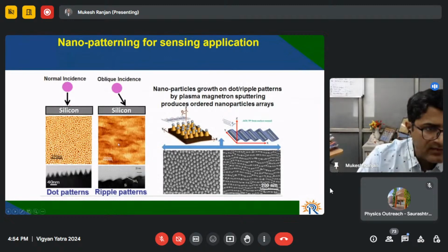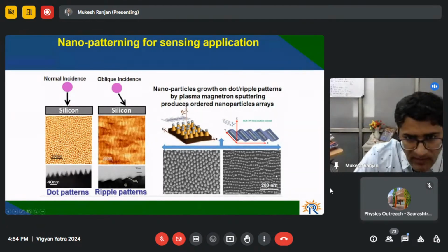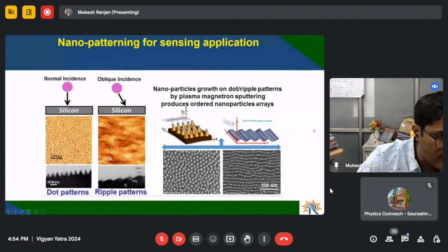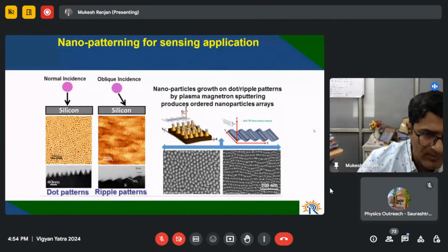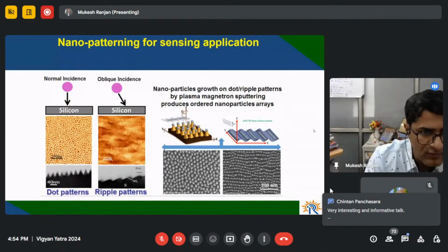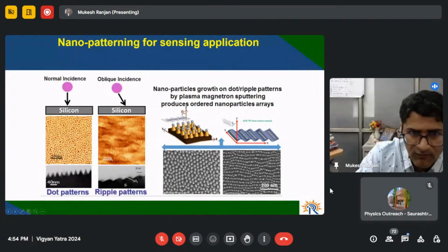Once we make this kind of pattern on the surface, it can be used as a template for growing nice chains of nanoparticles. Whenever we talk about nanoparticles, we use some kind of chemical processing where the problem is that the metal nanoparticles start to agglomerate, and a lot of residue of the chemicals used remains with those nanoparticles. So they are not pure in form.